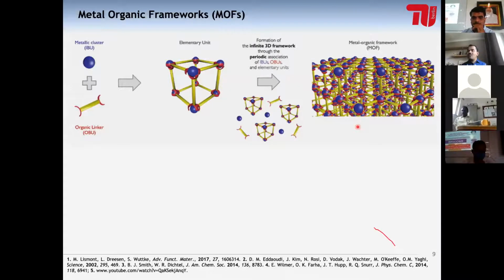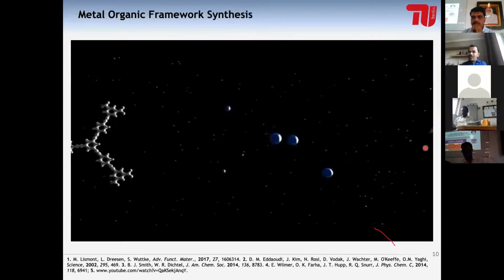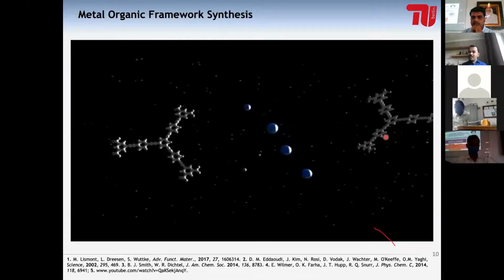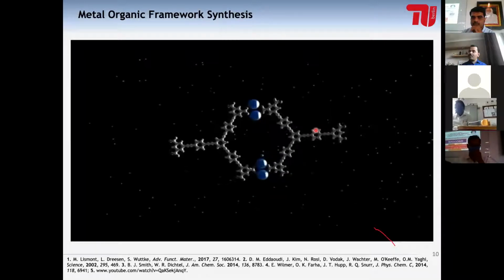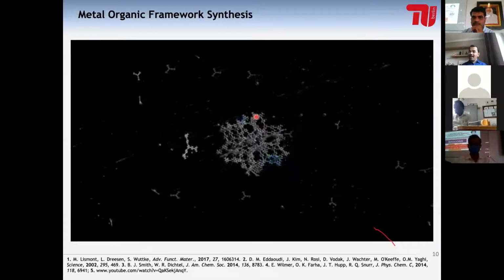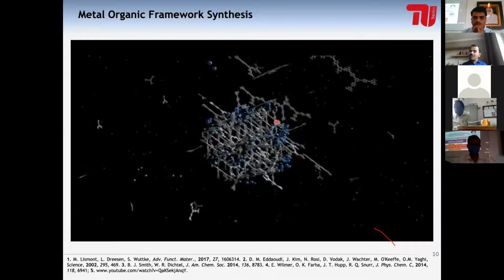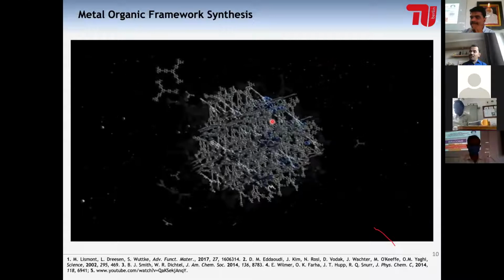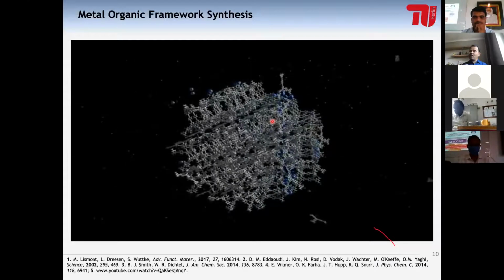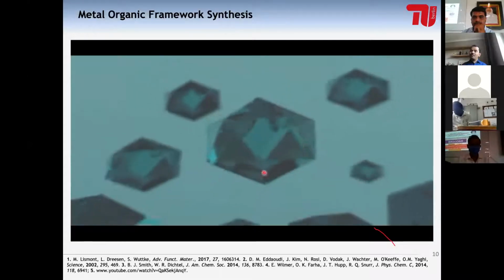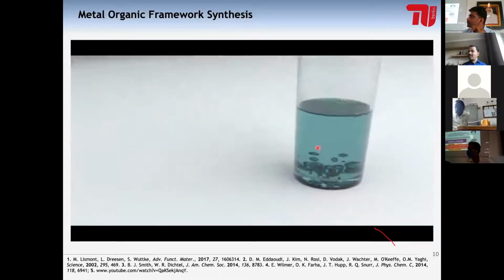How does this material get crystallized in a solution? I would like to show you a small movie where you can clearly see how this material starts forming. In a solution, these organic linkers start approaching the metal centers and start forming coordination bonds. With time, they start growing into three dimensions. They grow their molecular weight, but while growing, they put pores inside, which are perfectly ordered pores. So we exactly know where the pores are and where they are not. Once the molecular weight grows, these materials form beautiful single crystalline materials, which can be characterized by single crystal X-ray diffraction analysis.